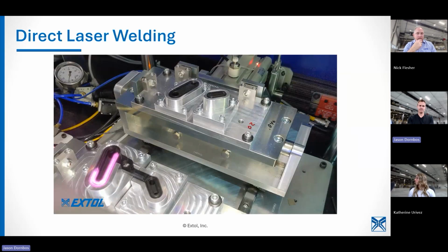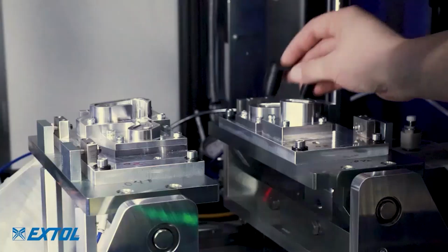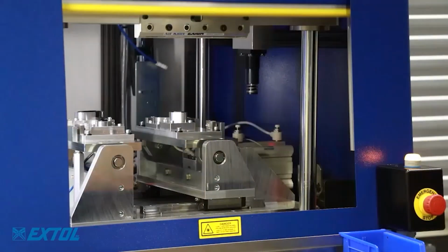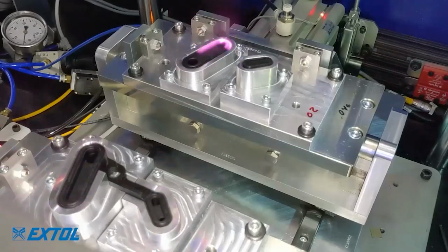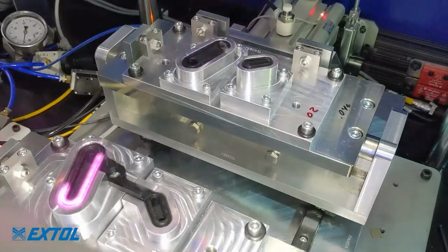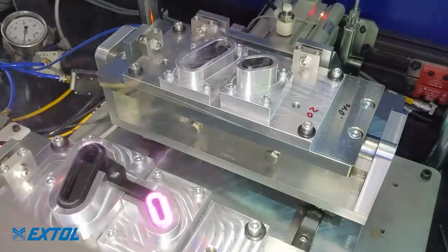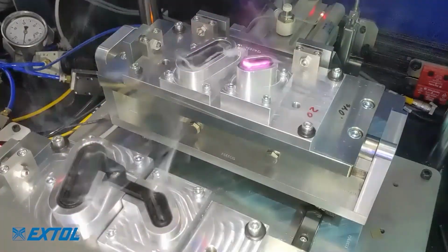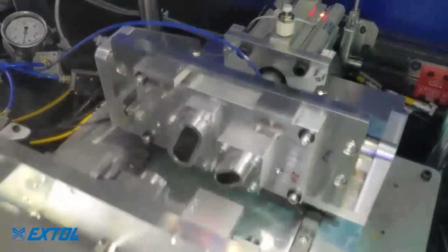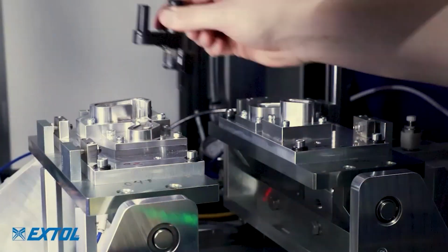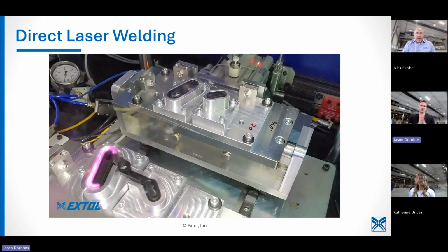I'm putting Jason on the spot. This is a direct laser application. So you'll notice the smoke. But here, there's no intimate contact because we're applying the energy directly to both sides of the assembly and then bringing them together. Right. So you get the smoke because there's nothing to keep it from oxidizing. And you still get a good weld because we're applying the pressure afterwards.